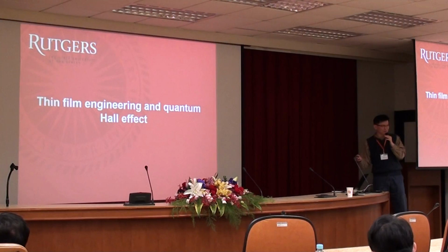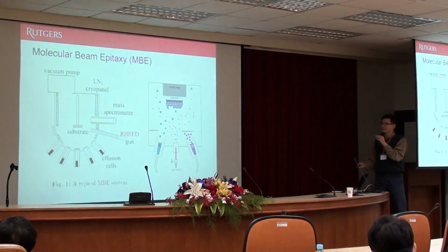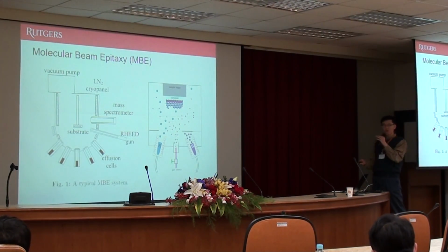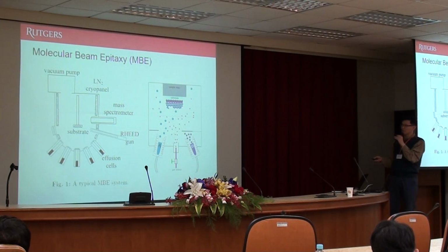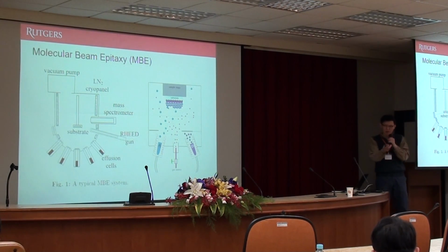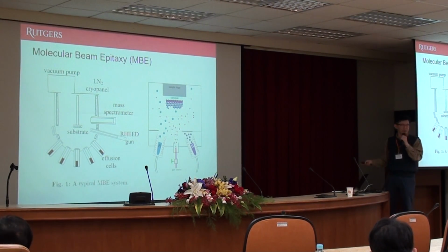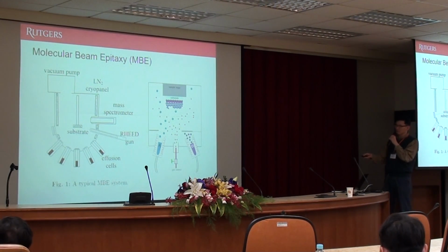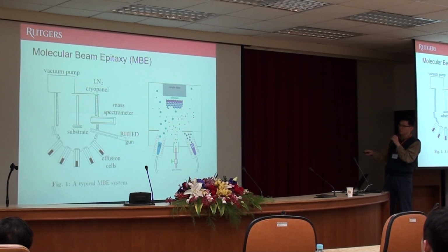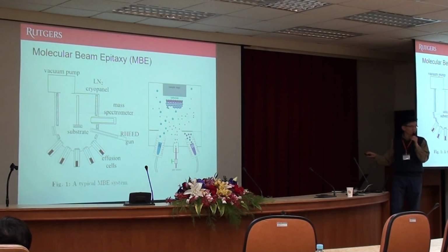So as we saw, the thin film has a hope. How do we make it? The tool we are using is molecular beam epitaxy, and it's very simple conceptually. This is thermal heat. It's like you just heat your water, then water evaporates. So it's like that. You heat whatever the element, for example bismuth and selenium. You heat bismuth, it evaporates. You heat selenium, it evaporates in a very good vacuum. Then you form bismuth selenide on your substrate.